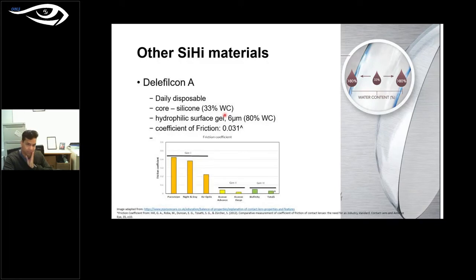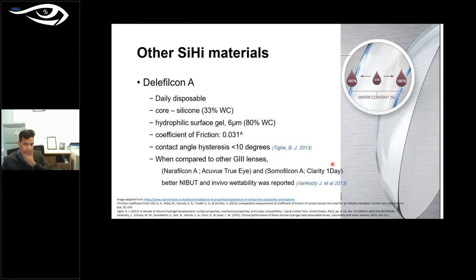If I add this in, the coefficient of friction is pretty low. As we have already discussed, if the coefficient of friction is lower, this should lead to more comfortable wearing of contact lenses. I'm not sure from a practice point of view how you see Total Dailies lenses in terms of wearer's comfort. Other studies looking at the contact angle hysteresis found it to be less than 10 degrees. To my understanding, there's no lens at this stage which beats that contact angle hysteresis, which is so low. This is a generation 3 lens, and when compared to other generation 3 contact lenses, this particular lens outperformed in terms of wettability and also breakup time.